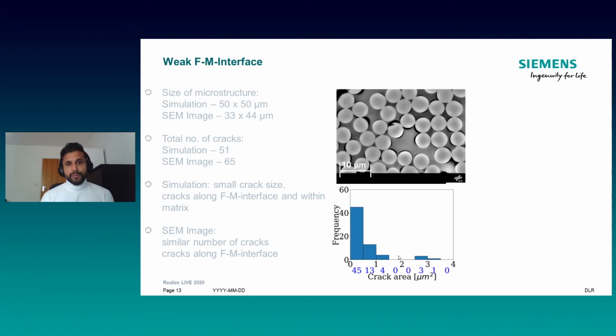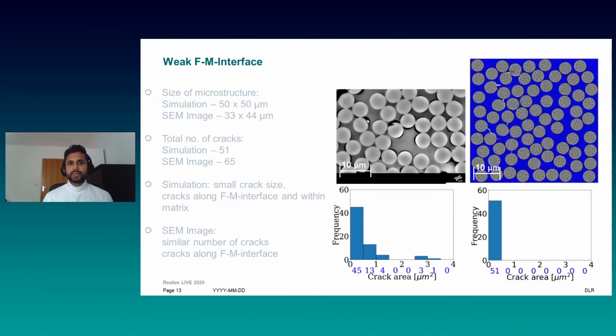So now if we compare the SEM image of a weak fiber matrix interface, we can see there are cracks, the black areas which you see here on the screen, and they are in the region of one micrometer square, right? And when we compare the simulation results with this particular SEM image, we can see even here the cracks are present on the fiber matrix interface, and the amount of cracks present in this particular microstructure is comparable with the SEM image.